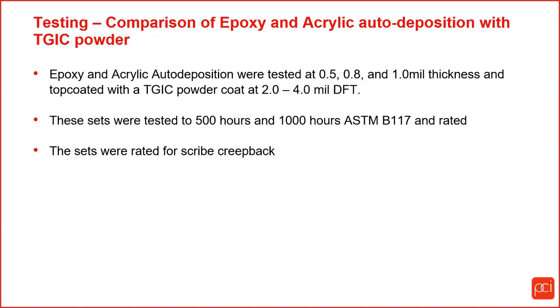Okay. So what testing was completed? We completed a comparison of epoxy and acrylic auto deposition with TGIC powder cover coating over it. The epoxy and acrylic auto deposition were tested at 3 different film thicknesses, 0.5, 0.8, and 1 mil thickness, and then top coated with a TGIC powder at 2 to 4 mil thickness.